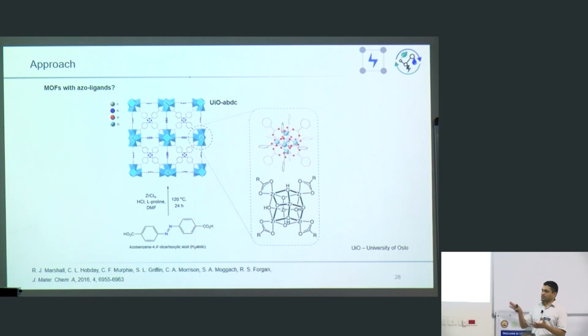It's known to have resistance to different pH conditions. It's thermally stable as well, and it's got these other properties of porosity, functionality, and other things. So if you produce this particular cluster of zirconium oxygen, this is going to be very, very stable. So if you have to go to the lab and prepare a MOF, and you don't know where to start with transition metal, if you know your ligand donor is carboxylate, a good choice would be zirconium. Just start with zirconium. You're more likely to get a very stable system.